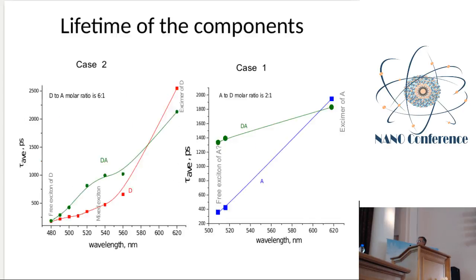So we observe, if we look at different components of the mixed solution, we observe the delay of energy, delay of lifetimes. For example, delay of lifetimes of donor in the presence of the acceptor, as I told you before. And also we observed the significant delay of lifetime of J aggregates of the acceptor. That means that in the mixed solution we have something new, something different from the pure J aggregates.